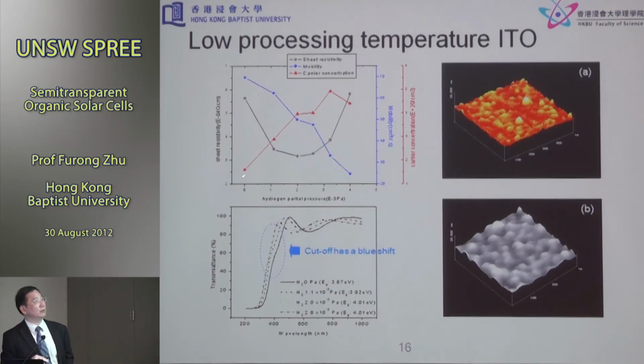So you could tune it, because the conductivity or the sheet resistance is essentially the product of carrier concentration and charge mobility. And you see that there's a large window where you can tune the conductivity of the material, where you achieve the lowest sheet resistance you can have for solar cell applications. Then you can use that as an interlayer in integrated or stacked solar cells.